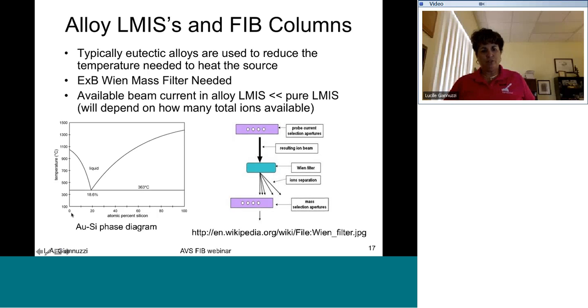So this is a gold-silicon phase diagram. So this is gold, this is silicon. So what these lines show you are the melting points for each of these elements individually. So the gold is up here close to 1100 degrees C. The silicon is way up here, close to about 1400 degrees C. So that would be a real pain in the neck to try to heat those up. So if we combine the two and use the composition of 18.6 atomic percent silicon, we can lower the melting point of this mixture to only about 363 degrees C. So we can operate this mixture of this composition at a much lower temperature than we would either gold by itself or silicon by itself.